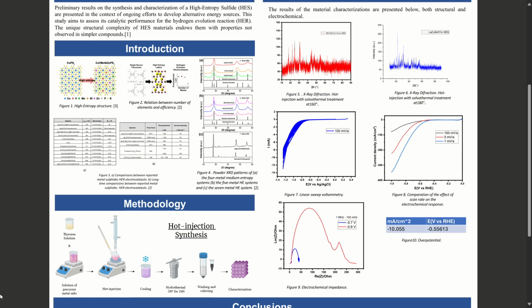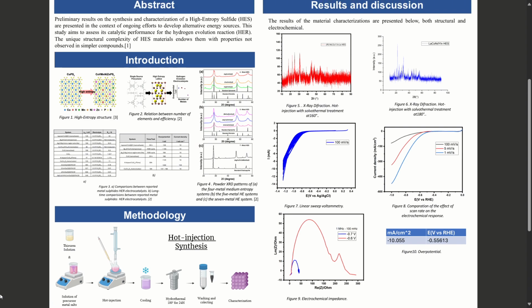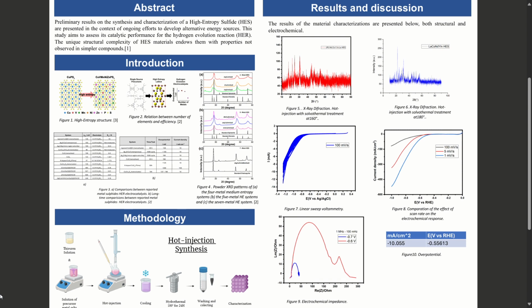Once the material was obtained, we performed X-ray diffraction to analyze the crystalline phases and structural order, and electrochemical characterization, including linear sweep voltammetry to measure overpotential and catalytic activity, electrochemical impedance spectroscopy to assess charge transfer resistance, and a stability test to evaluate performance over time and under cycling. This combination of structural and electrochemical characterization provided a complete picture of how the material behaves as an electrocatalyst.